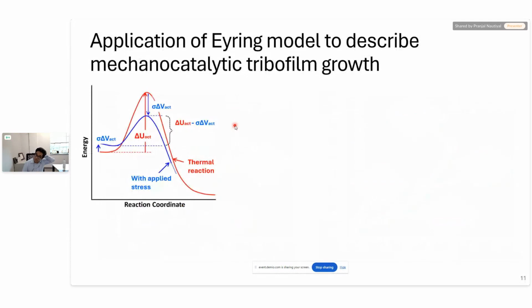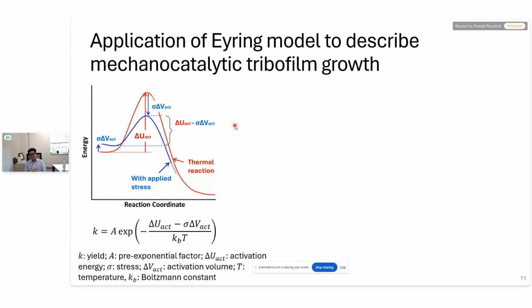So going back to the potential energy surface I showed at the beginning of my talk, as I said, there is an energy barrier that needs to be overcome for any chemical reaction to take place, and mechanical stresses lower this energy barrier. And this can be expressed by this Arrhenius style equation, a more complex version of the equation I showed you before. So essentially, there is an activation energy that is needed for the chemical reaction to take place. When mechanical stresses, here represented by sigma, are applied, that is going to reduce the effective energy barrier.